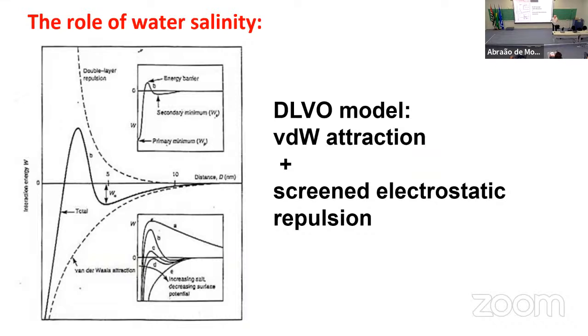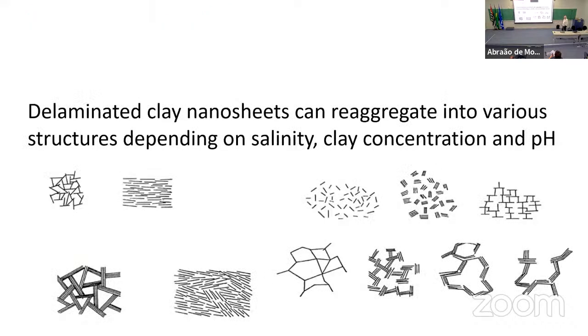I mentioned that there is some interaction between the platelets because we observe some fixed distances, even in suspension. And that, in principle, comes from the DLVO interaction, which is van der Waals attraction and electrostatic repulsion screened by ions in the water. So how much salt you have in the water governs distances between clay platelets in suspension. When you add more salt, these nematic suspensions can re-aggregate. If you add much salt, van der Waals eventually can win. And then you can get re-aggregation in various types of structures, depending on salinity and pH. So I won't go into that, but that can happen.